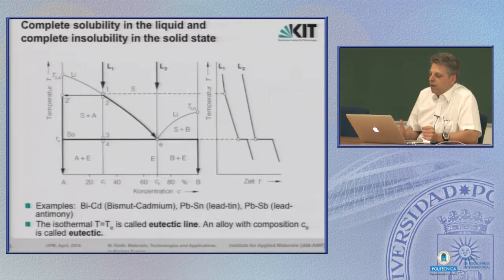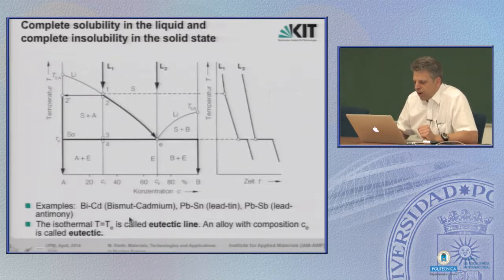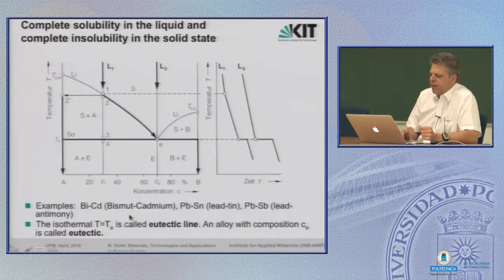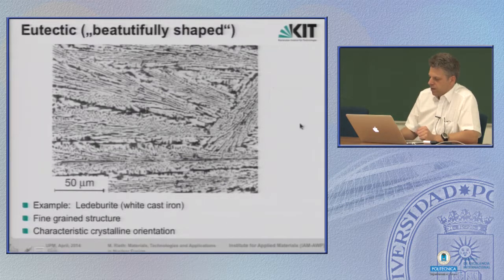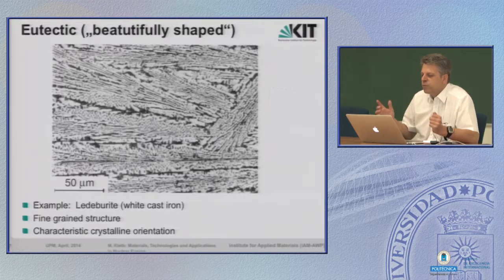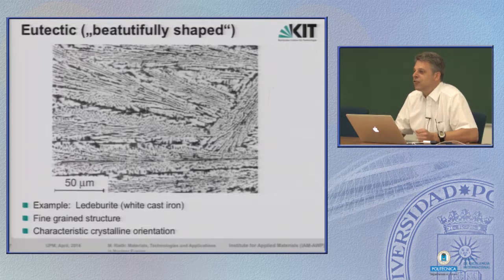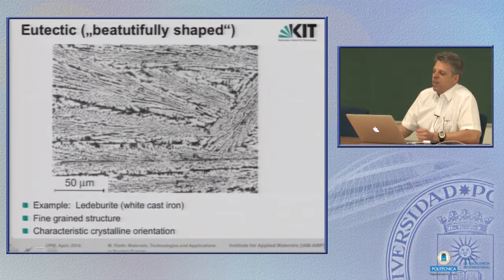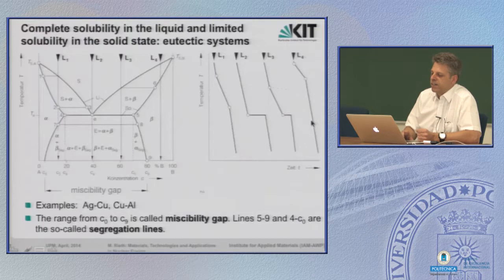Well, for such specific phase diagrams, there are only a few examples. Bismuth cadmium is one, or lead tin, or lead antimony. That's a few of them. The microstructure looks very specific for this eutectic. Eutectic in English means beautifully shaped. I'm not so sure whether I consider this as beautifully shaped, but at least it's interestingly shaped. We come back to that later. There is also in steels, we know this from the ledeburite phase, that's cast iron, which looks similar to that.